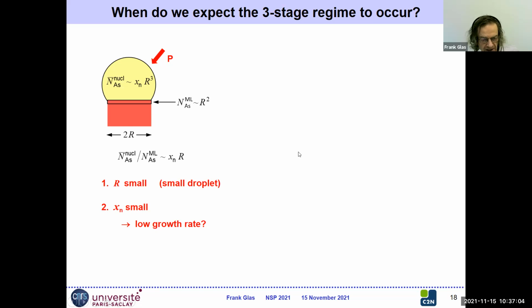And actually, I must say that up to now in Nanomax for Wurtzite monolayers, we only observed this three-stage regime. In other words, we never observed up to now the regime that we studied 10 years ago, where we could form instantaneously a full monolayer. So this tends to mean that we never have enough arsenic atoms in the liquid at nucleation to form a full monolayer.